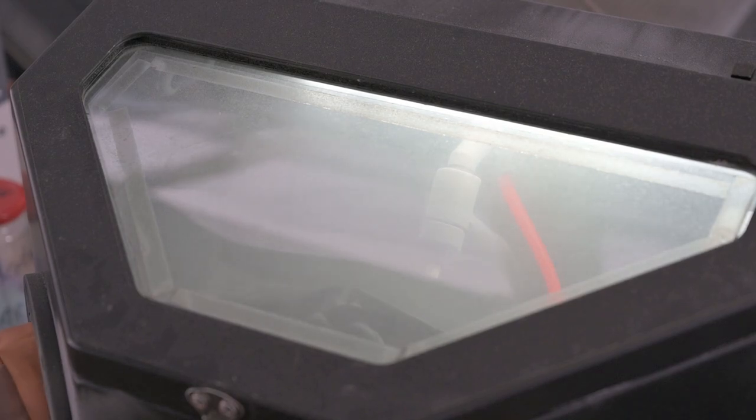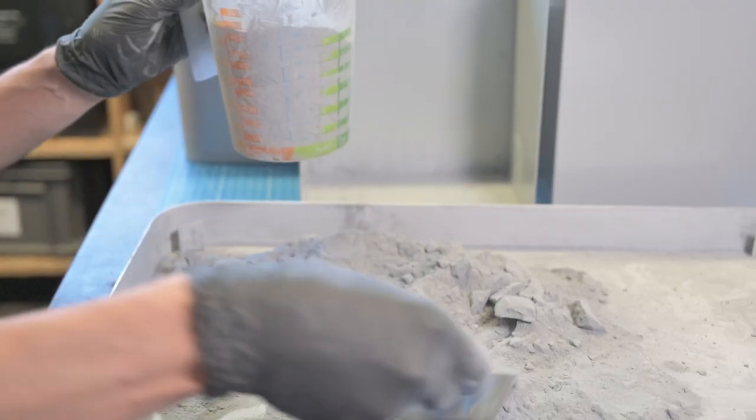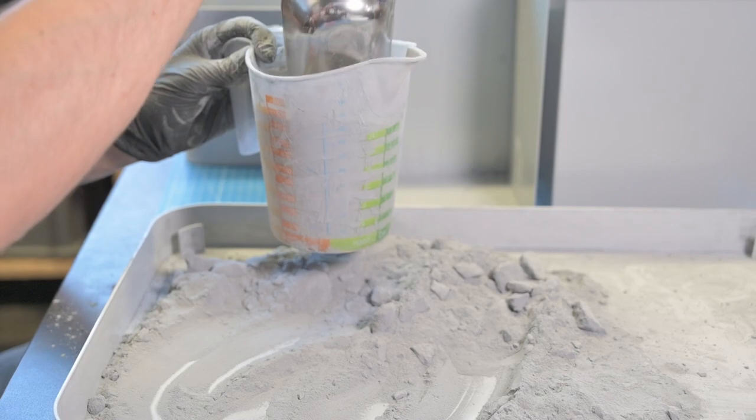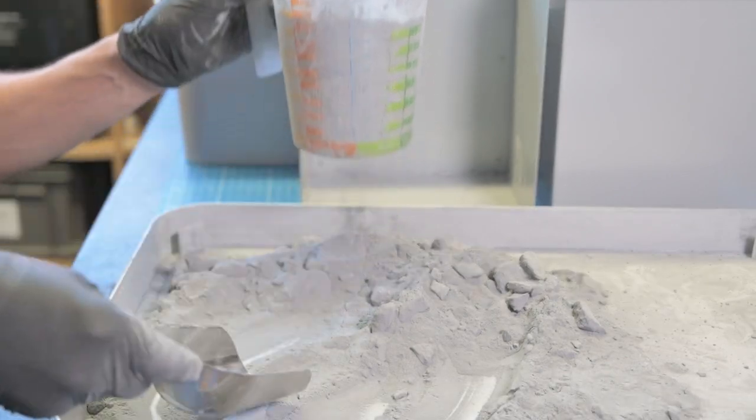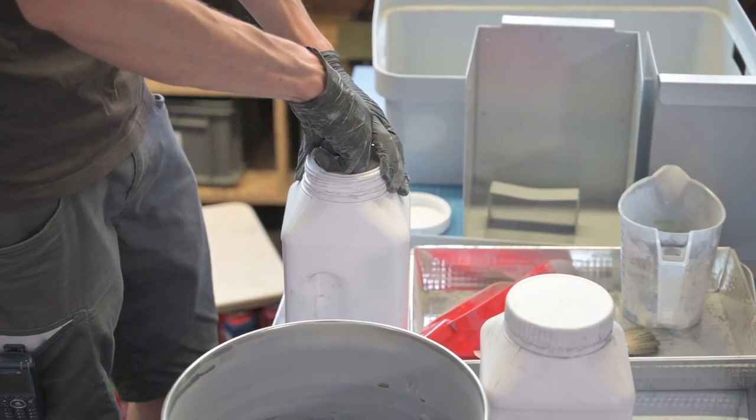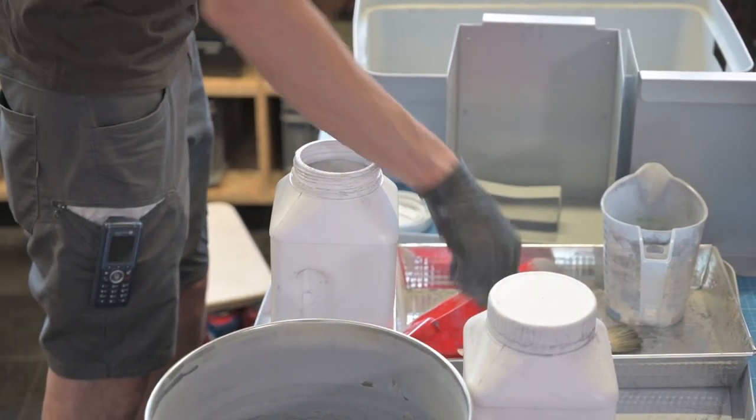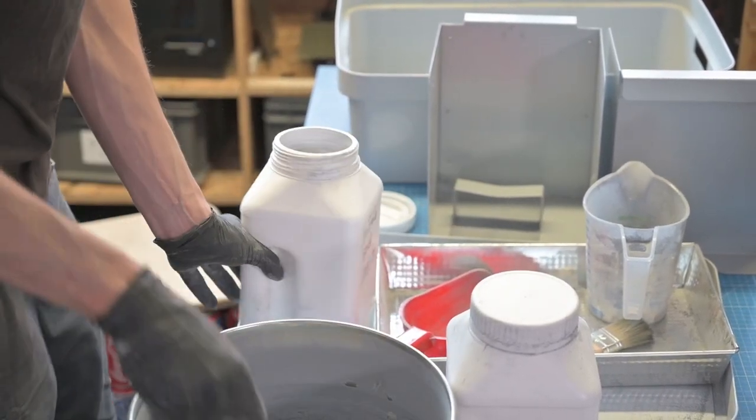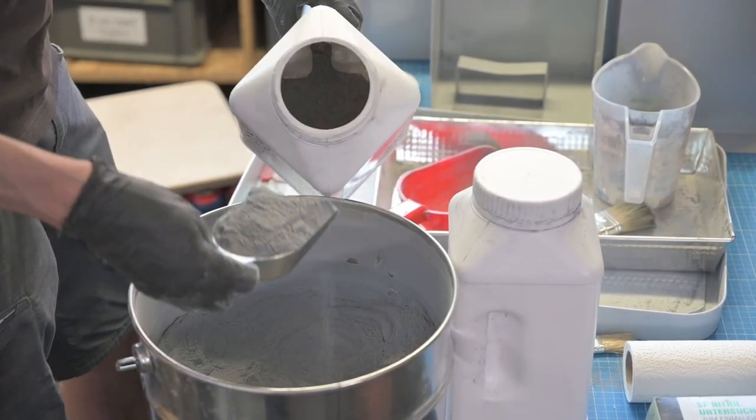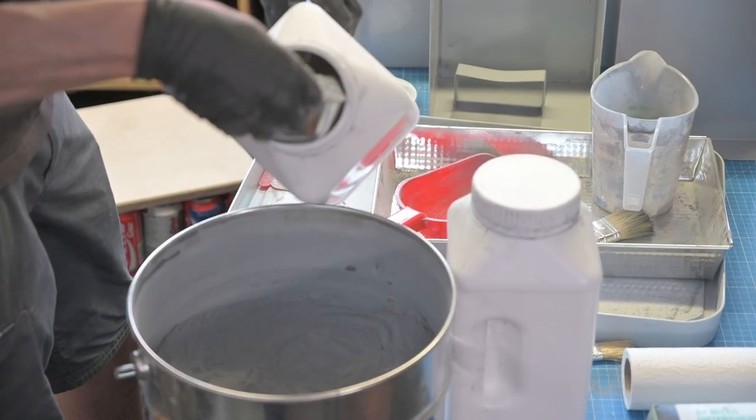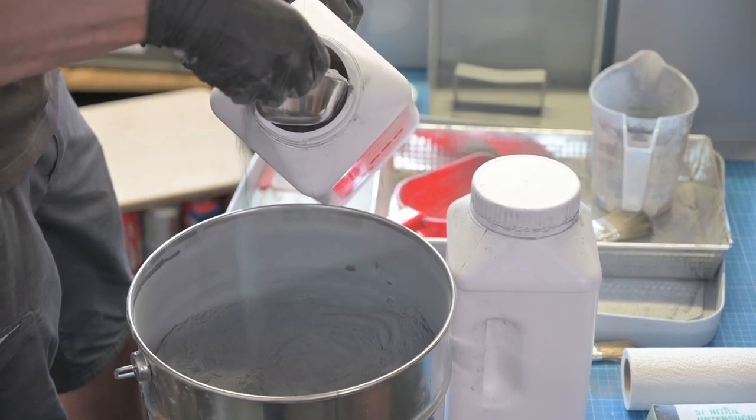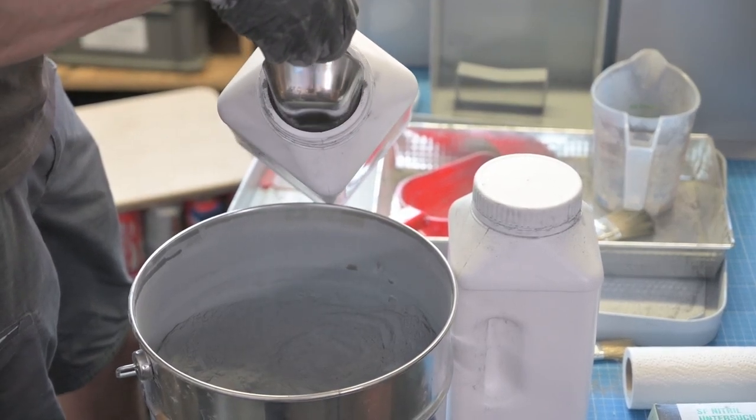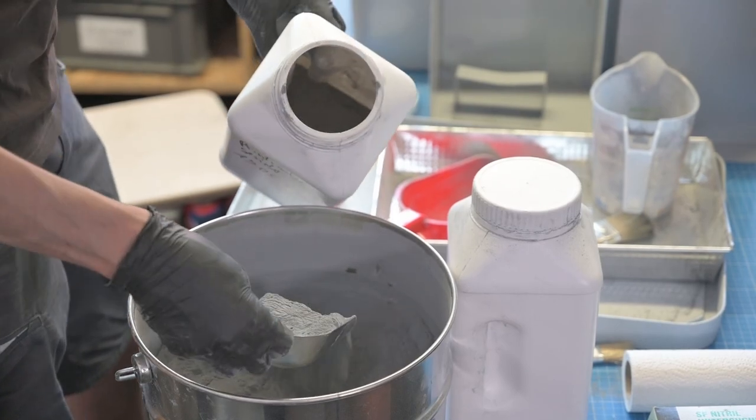Now the model is finished and a lot of powder that has not yet been used is left over. This mixture can then be used again for future printing processes. For this, unused powder must be added so that in future printing processes the powder is not too thermally stressed.